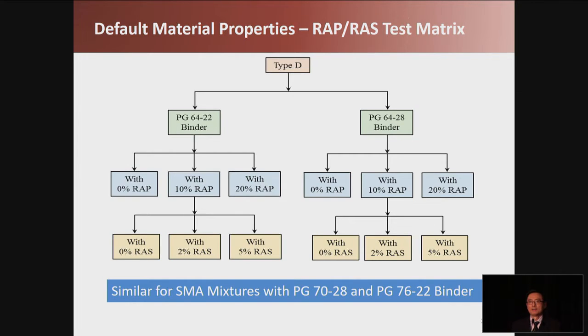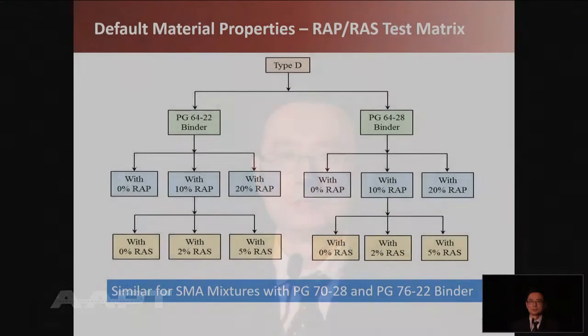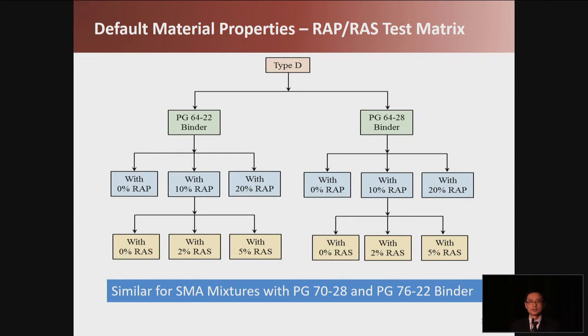So to make the program more convenient and more practical, we try to develop the default value system. For example, for the material property default values, we have developed the properties for almost all Texas typical mixtures. And in this study, we focus on the influence of the RAP-RAS contents. So here is an example of the test matrix to determine the default values. You can see, for example, this is Type D, the dense-graded mix. We have different binders, and then for each binder, we have different RAP content and also different RAS content. Similarly for the SMA with different binders. So this is the test matrix we did, to try to find some relationships for these material properties.